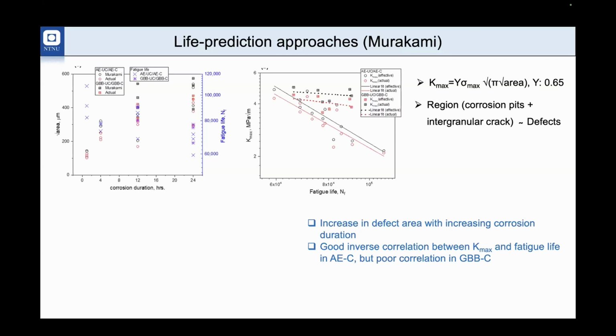And if you look at the graphs here, you will see that with an increase in the corrosion duration, of course, the defect size will increase. And when there is an increase in the defect size, the fatigue life decreases. But as I mentioned earlier, this increase in defect size and decrease in fatigue life is not exactly synchronous. And this becomes more clear if you look at the graph on the right-hand side. Here, from the same defects, we measured the Kmax and plotted the Kmax with the fatigue life.